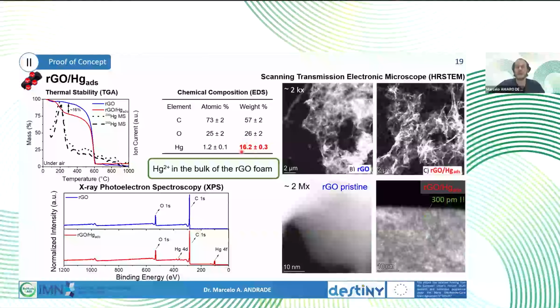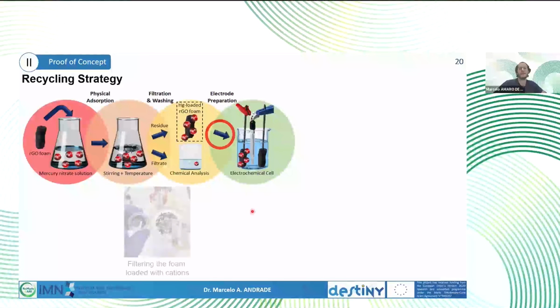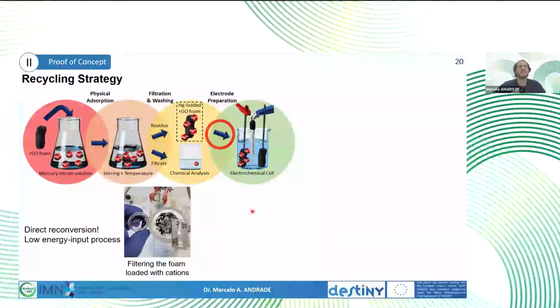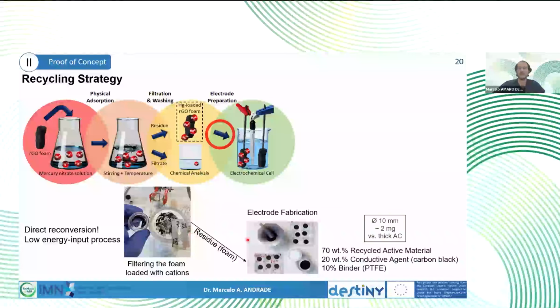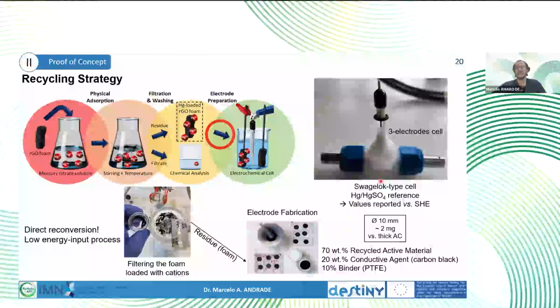And on these first tests, it was around 16 weight% of mercury by TGA and EDS. Mercury was mainly in the bulk of the RGO foam. And as I said, we wanted the recycling process to be as straightforward as possible, so low energy input. So recovering the RGO foam was directly from filtration after washing with distilled water, and the residue was directly transformed into electrodes without heat treatment or chemical treatment. And these electrodes were tested in Swagelok type cells against a thick activated carbon electrode.